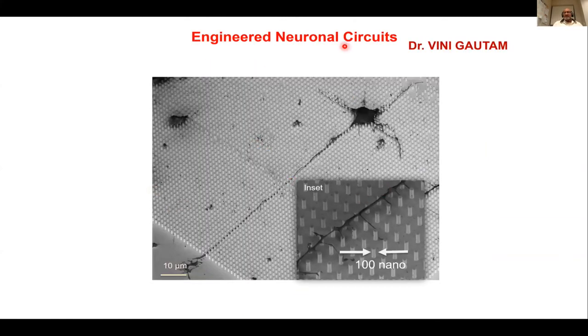And in fact, Vinny has spent about 3 years optimizing these things. We tried to use these indium phosphide nanowires and grow neuronal cells on top of them. You can see the cell body of this neuronal cell here, and these axons really like to follow the patterns of these indium phosphide nanowires very nicely. You can see the close-up of some of the dendrites coming off these axon structures as well.